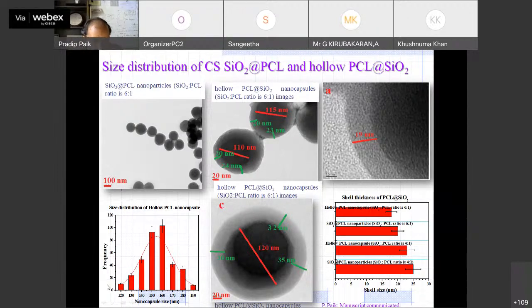So you can make different sizes of particles. If you see here, the light gray color is the shell, then the solid deep black is the silica particles, and then the liquid layer is also there. Liquid layer means this is the gap. Nanoparticles of silica 100 to 110 nanometers, and there is a liquid gap. If you can take out these things, I will also show it.